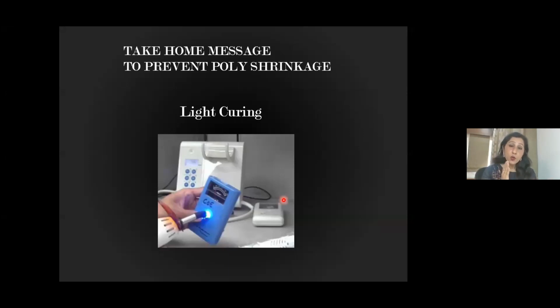So if you want to buy a curing light, always ask what wavelength your curing light works on. If they work between this 300 to 500 nanometers, then only does it make sense to buy them. And especially 468 nanometers, where the camphoroquinone gets initiated. We now have so many photo initiators, but the one that is used widely is the camphoroquinone, and that gets initiated at 468 nanometers.